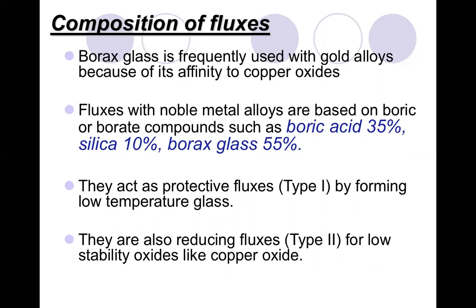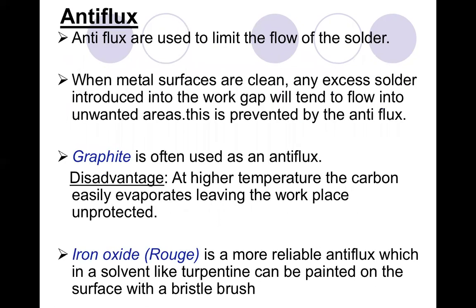Fluxes with noble metal alloys are based on boric and borate compounds. This is very important. You should remember this boric and borate compound thing, that is boric acid 35%, silica 10%, borax glass 55%. So they act as protective fluxes, that is type 1, by forming low temperature glass. Okay, and type 2 are also reducing fluxes, and they are for low stability oxides like copper oxide. So type 1 are protective fluxes, type 2 are reducing fluxes.